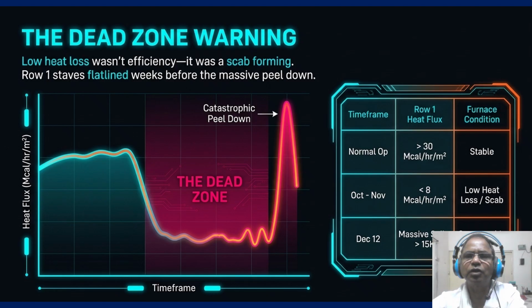Now look at the table on the right. Normal operation is over 30 megacalories. But in October and November, we drop below 8. The so what is the catastrophic peel down. You see at the end of the timeline, when that scab finally breaks off, it drops a massive cold mass into the hearth, causing a temperature spike that is actually a herald of death. You must treat a heat flux flatline as a critical warning, not a victory.